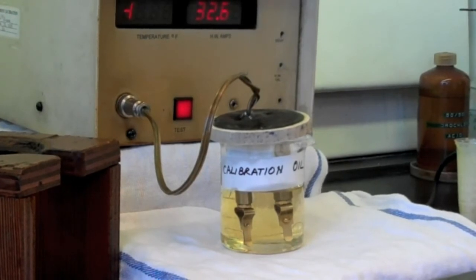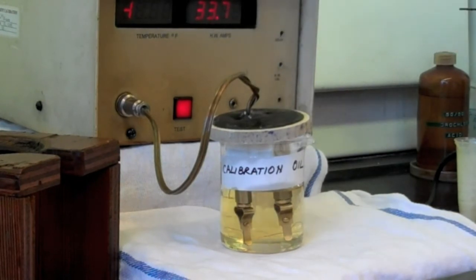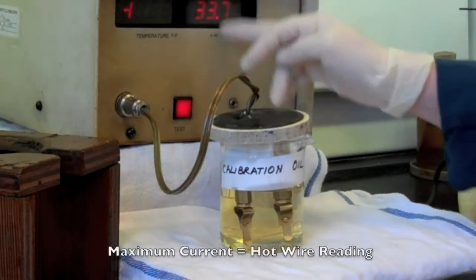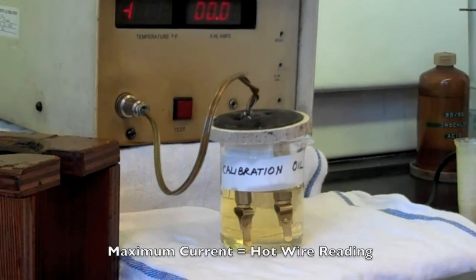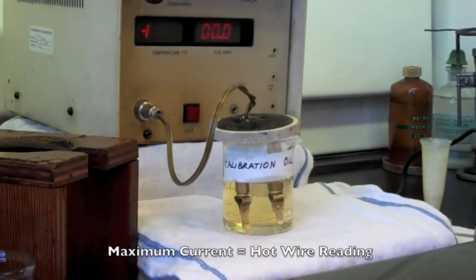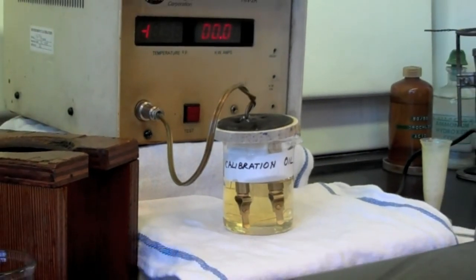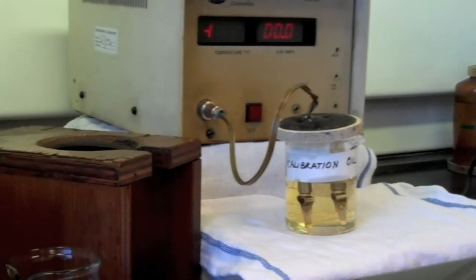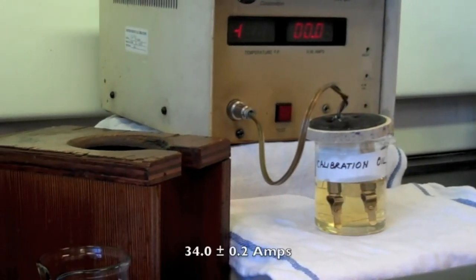This maximum current that the wire can take before burning out is locked on the display, and it's taken as the hot wire reading. 3 such determinations are taken, and the average value is considered to be the quench speed of the oil. For the calibration oil, the value that we are expecting is 34 plus or minus 0.2 amps.